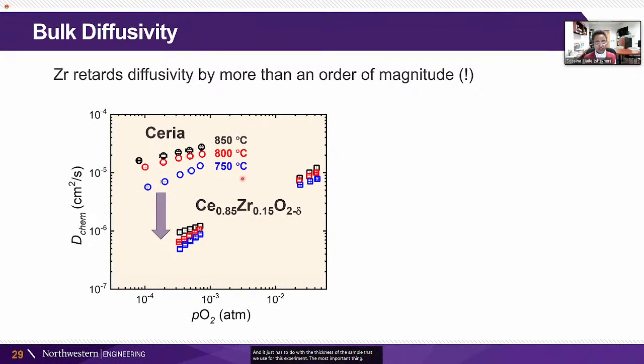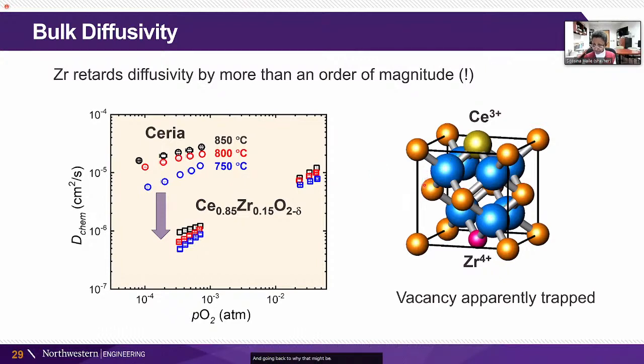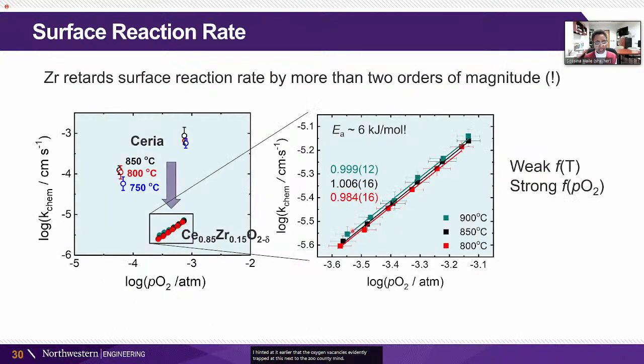The most important thing is to show you that introducing zirconium, despite the fact that it creates all these vacancies for us, causes the diffusion coefficient to go down. This is an earlier measurement that we had for ceria, a dramatic decrease, an order of magnitude decrease in the diffusion coefficient. And going back to why that might be, I hinted at it earlier that the oxygen vacancy is evidently trapped next to the zirconium ion. And if we look at the surface reaction rate constants, it's a similar story. In this case, again, decreased by more than an order of magnitude, and surprisingly, a very weak temperature dependence here. So that was quite surprising to us.